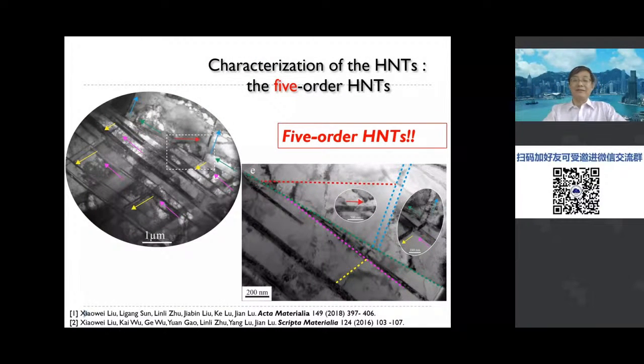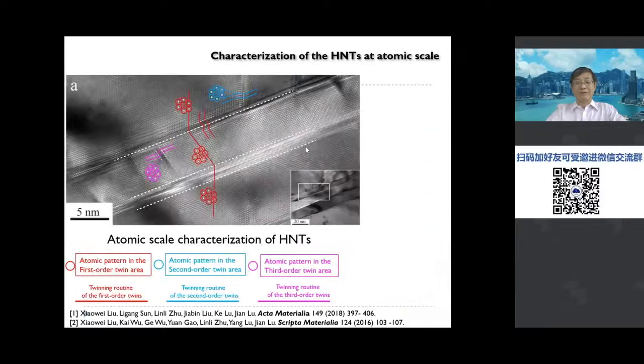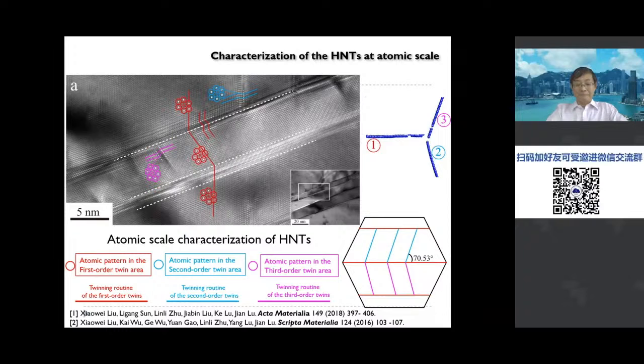So how to generate a higher density nano twin? Increasing the order of nano twin is a very important issue. So on the model material, which is pure silver, we have successfully demonstrated how to obtain the fifth order nano twin. And basically, by using the in situ mechanical test and also diffraction, we can easily demonstrate we obtain the fifth order twin. And this is a good management of different levels of twin spacing. So basically, to generate the next order twin, we need to have a large enough twin spacing to generate the next order's twin.